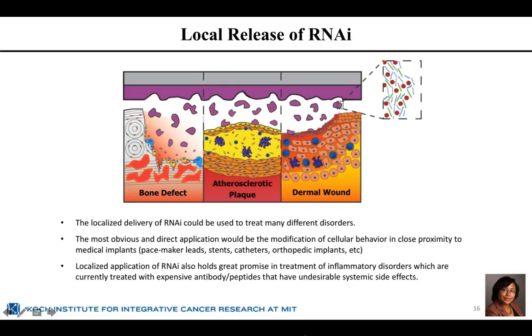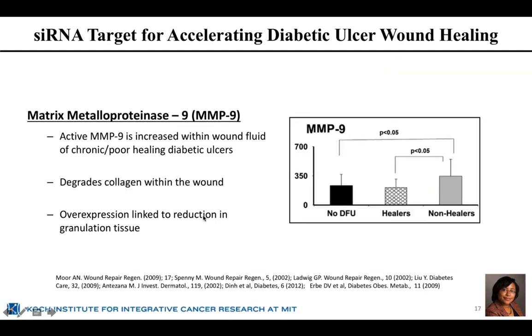All right, I'm going to give a very brief second example of layer by layer from a large surface. We can also release siRNA directly to wounds using the same kind of approach. And the reason that we might want to do this is to correct the overexpression of specific genes that might occur in wounds because of some sort of change in the metabolic function. For example, for diabetics, chronic wounds are a common problem. And in these hyperglycemic patients, there is often overexpression of the collagenases that break down tissue at early stages. One of these collagenases is MMP9. It actually breaks down collagen, and at early time frames when we really need to be laying that collagen down to generate a matrix for wound healing.